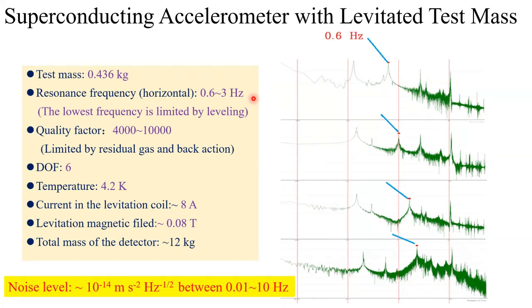The limitation is mainly the residual gas, because when we adjust the current in the coils, we use heat switches, and there needs to be some residual gas as heat exchanging gas. This causes a lot of damping to the test mass, so the quality factor is low. If we pump this gas out, I think we can get a much better quality factor. And every test mass has all 6 degrees of freedom.